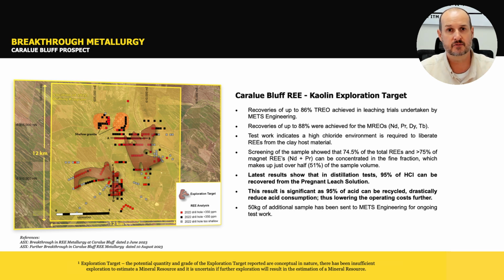The second breakthrough we had was that we realized we could recycle about 95% of the hydrochloric acid that we were using to leach off those rare earths. So those are two techniques that we can use now to significantly bring down the costs of processing those rare earth bearing kaolin clays. The next step after this will be then to see if we can economically extract enough of those impurities to then be able to precipitate a good mixed rare earth element carbonate. So that's on the agenda for the coming months to see if we can do that.